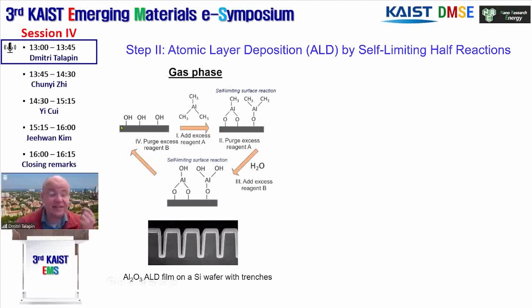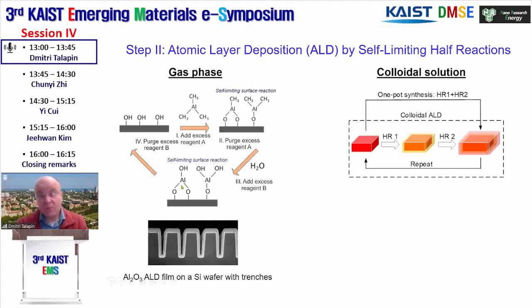The key idea here is that the growth of a new phase, like in this case, the aluminum oxide phase, is divided into two half reactions where each half reaction is self-limiting. So when you expose the surface of a silicon wafer to an excess of trimethyl aluminum, you will grow a single layer of alkyl aluminum fragments, and the reaction will stop there. A second layer will not grow. And then you can do the second half reaction and keep going, growing conformally one layer at a time.